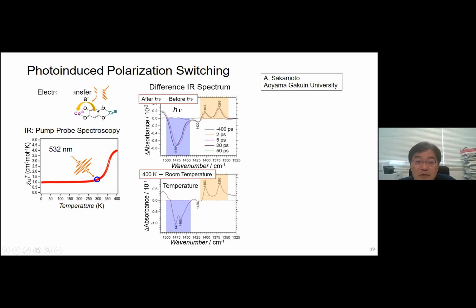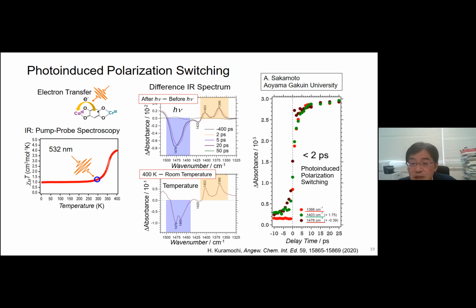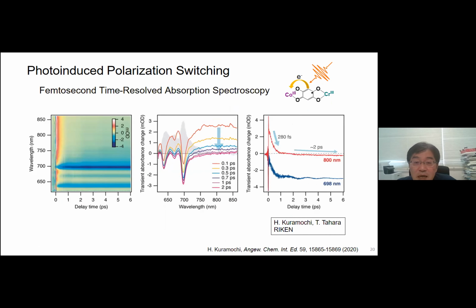This means electron transfer is induced by photoirradiation. And this electron transfer is completed in less than 2 picoseconds. So this means polarization switching occurs in less than 2 picoseconds. And to characterize the faster process, we measured the photo effect using femtosecond time-resolved absorption spectroscopy. And as shown here, after irradiation, absorption changes, and it decays with a time scale of 280 femtoseconds. So this means polarization switching is induced on this time scale.